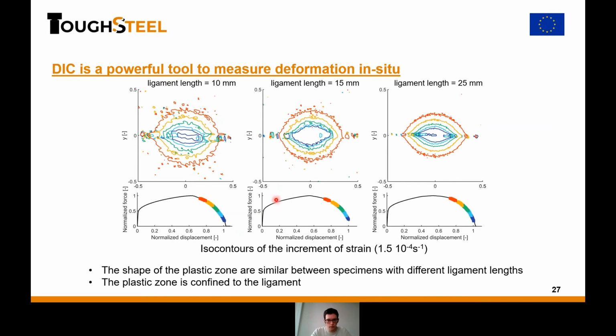The second thing I like to do is draw these types of isocontours. This is slightly different than before. Instead of checking from the beginning, I checked after crack propagation. And instead of drawing the total deformation, I draw the increment of strain. So for each color, it's at the beginning of the segment and at the end of the segment that I take the difference in strain. And again, I make a contour so it's easily readable in the figure. What this allows me to see is that I can check the shape of the plastic zone, and this way I can check that the plastic zone is similar, or geometrically similar, between different ligament lengths, which is also a criterion for the validity of the essential work of fracture method. So in this case, I have a test with a ligament length of 10 millimeters, one with 15 millimeters, and one with 25.